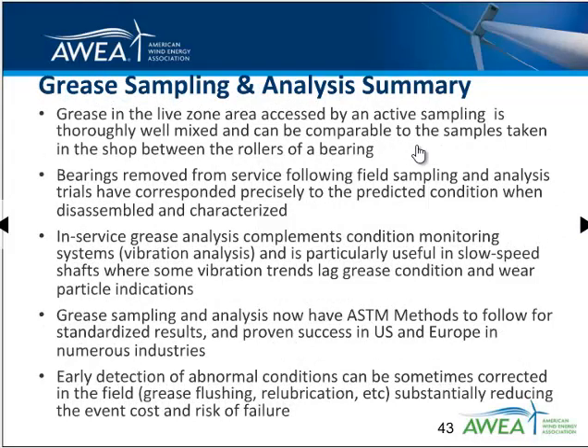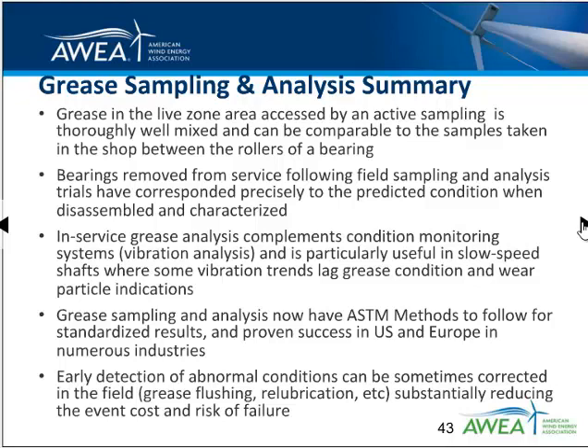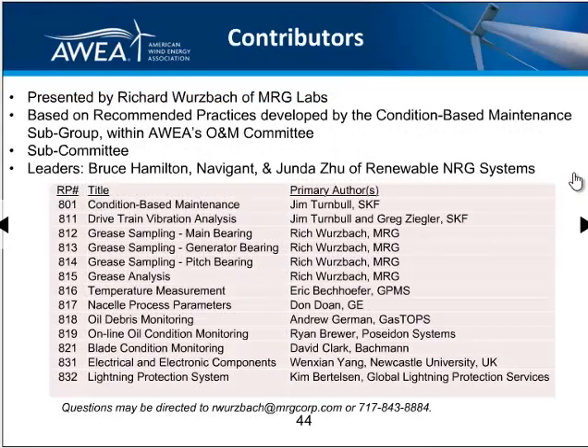To summarize: grease in the live zone area is accessed by active sampling and is very well mixed, comparable to samples taken in the shop between the rollers and the bearing — based on findings from the offshore wind industry work done in Denmark. Bearings removed from service following field sampling and analysis corresponded precisely to the predicted condition when disassembled. In-service analysis complements the condition monitoring system such as vibration, and is particularly useful in low-speed shafts where vibration trends may lag grease condition. Early detection can sometimes be corrected in the field by grease flushing and re-lubrication, reducing the cost and risk of failure.